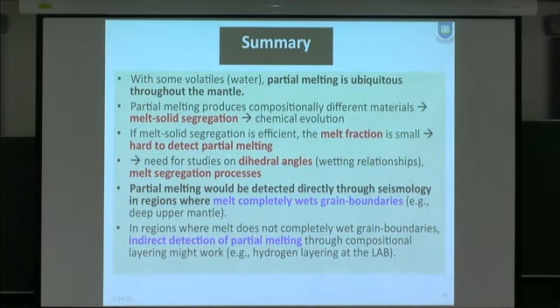So to summarize, with some volatiles, partial melting is ubiquitous throughout the mantle, and partial melting produces compositionally different melts caused by melt segregation, which causes, of course, the chemical evolution of this planet. And if the melt segregation is efficient, and if the melting is just caused by volatiles, the melt fraction you expect is very limited. And therefore, direct detection of partial melt by geophysical methods is going to be very difficult.